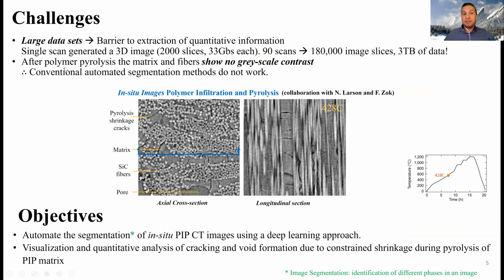Another challenge is that after pyrolysis, the matrix and fibers are silicon carbide and they have no gray level difference to them. You can easily see it in the axial cross-section here where you can identify matrices and fibers, maybe pores, but in the longitudinal section, you're really clueless to what you're looking at. So with these difficult images, conventional automated segmentations do not work. So something that can pick up on the features and automate the segmentation process is excellent, and part of the objectives here is to automate the segmentation.